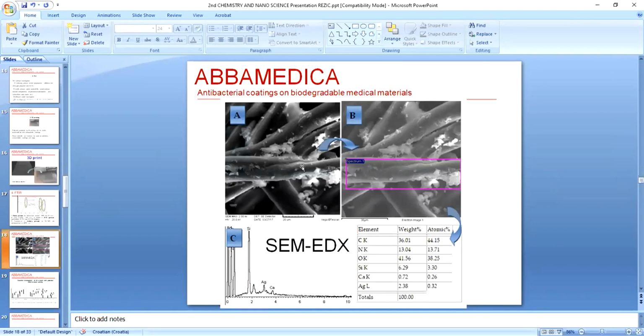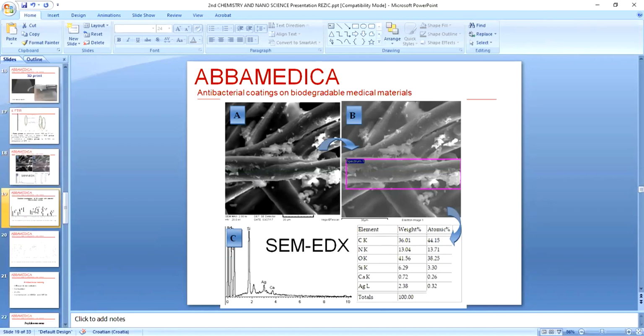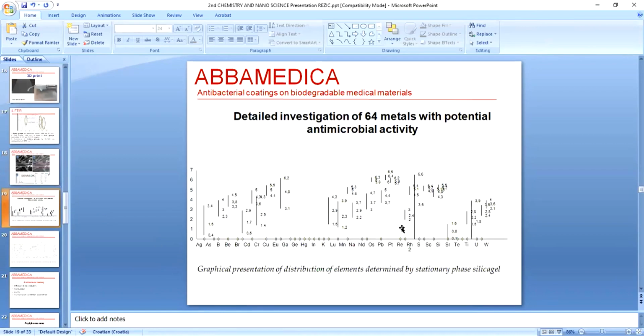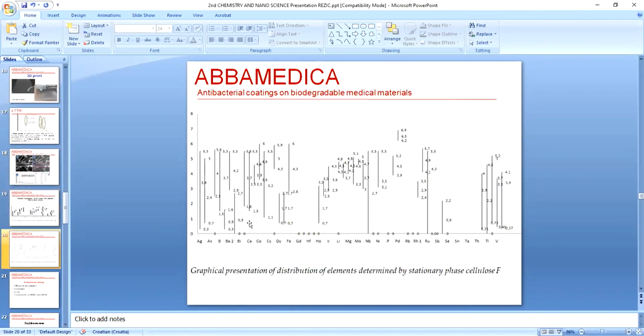And at the end, during characterization, a scanning electron microscope equipped with an EDX detector is very helpful too. Because firstly, we can make a microphotograph at a magnification of 100,000 or whatever we need, of the area along the surface of the polymer. And then we can produce an elemental analysis of this area and really see if our, for instance, silver nanoparticles or zinc oxide or any other are bonded to our polymer surface. Afterwards, we can make extraction and by chromatography detection see which type of element has been extracted from the surface and how efficient our new coating actually is.